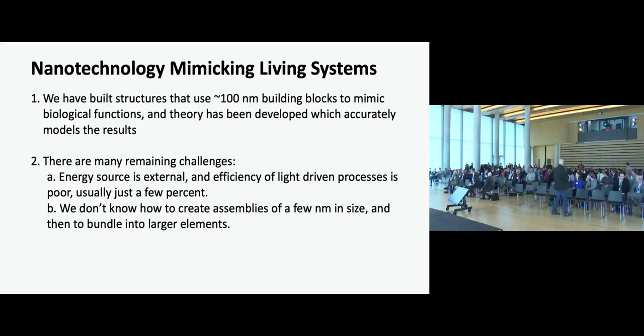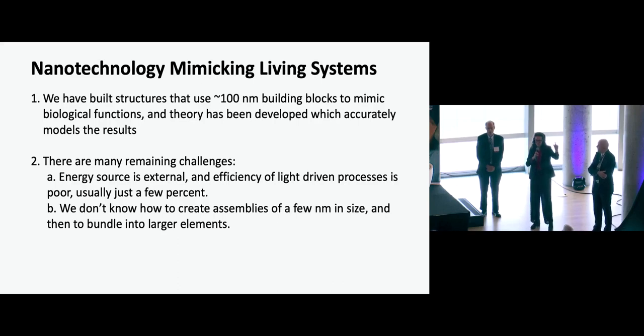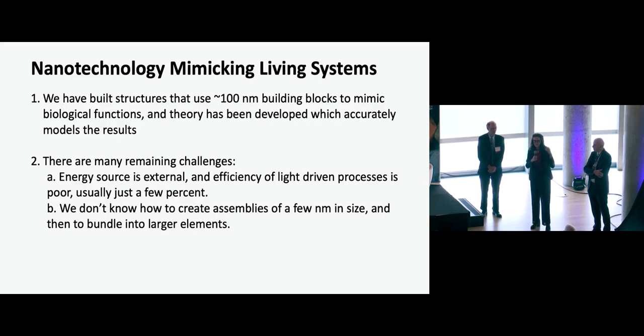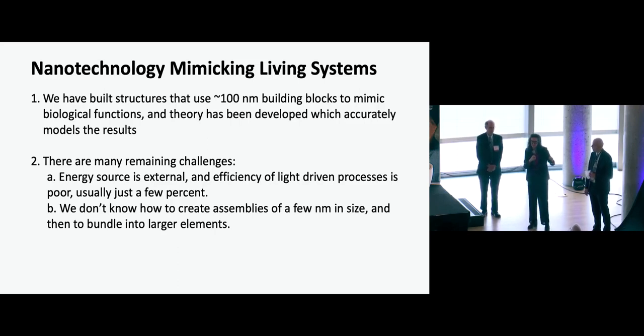Can you comment on the reliability of the light-based and magnetic-based movements? That's why I showed the film where the theory calculation matches the experiment exactly. We use continuum mechanics, which is a very robust field with very strong concepts. For example, you design the substrate so that it's not slippery, so it can walk rather than slide. We also know very well the laws of how much light transfers through the gel and water and how much gets absorbed—that tells you exactly how much bending will occur. Using polymer physics to calculate elasticity properties, which are very robust, the combination of all these makes it extremely reliable. You can design and direct these robots very efficiently.